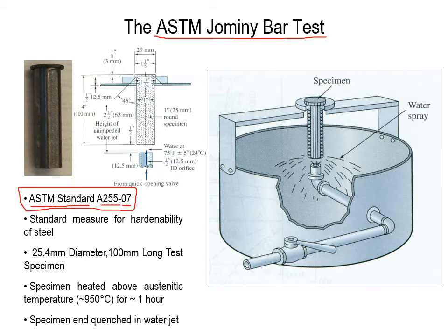So we can see above here we have all the specified dimensions for the test. Our specimen goes right here in the center. This is a standard measure for hardenability of steel. For our specimen, it's going to be a 25.4 millimeter diameter, 100 millimeter long test specimen that we're going to use for this. Now, the specimen is going to be heated up above 950 degrees Celsius for about an hour.